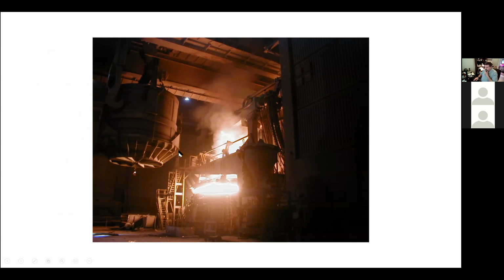So here you see the charging process. The furnace is starting to lift the roof, and it's going to swing this roof out of the way so that this bucket can come over and drop scrap in the furnace. Now, the reason why it sometimes takes more than one charge to make a heat of steel is that the bulk density of the scrap might be quite low compared to the bulk density of the liquid steel. So sometimes it takes two, or even, in the old days, I worked on one furnace where it took 5 charges of scrap to make one batch of steel.